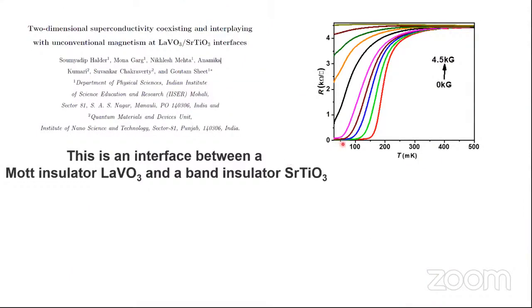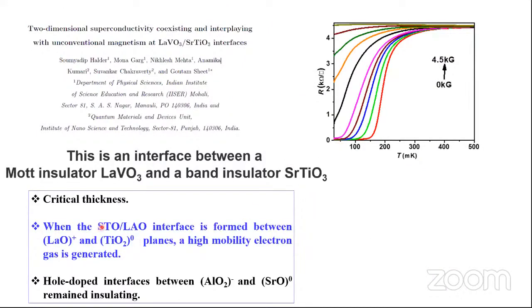I want to make a note here that even in the case of LAO-STO, it is known that superconductivity happens closer to the STO part of the interface. So it is possible that the superconductivity is coming from the superconductivity that is already known for STO, particularly delta doped STO. But that is okay for us because the entire STO does not become superconducting. Effectively, we get a two-dimensional superconductor, which is confined only at the interface, regardless of its origin.